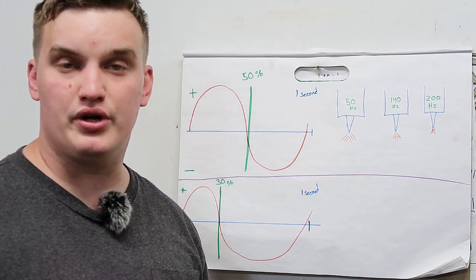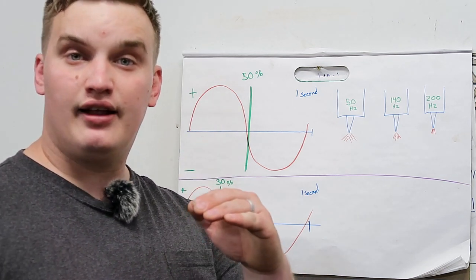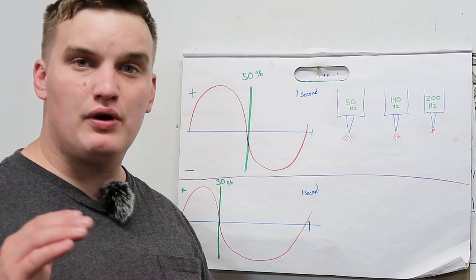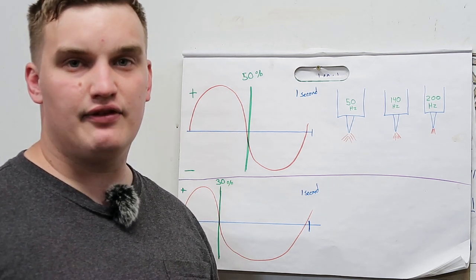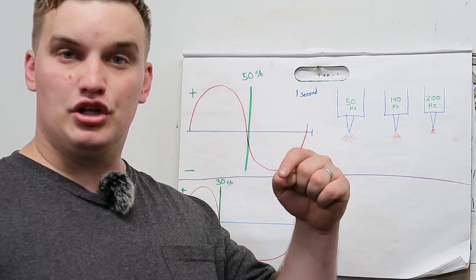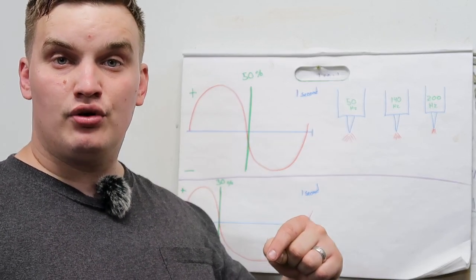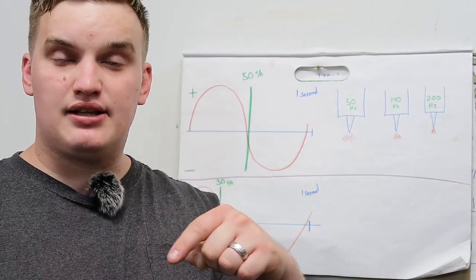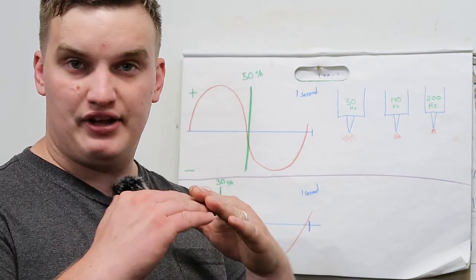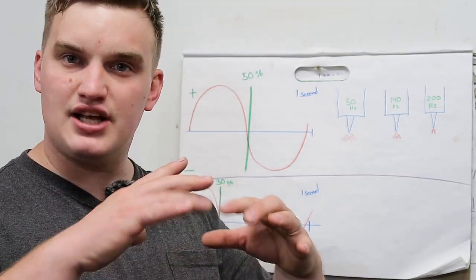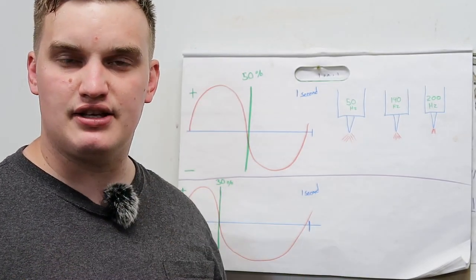and that's why we use AC current, because with aluminum we have two separate melting points. We have our oxide layer and our substrate. So if you tried to just weld this with DC negative, just like you would your mild steel, you would penetrate through and melt your base layer, but you wouldn't have enough heat to melt that oxide layer on the surface, and you just have this kind of molten yucky stuff sitting on the top.